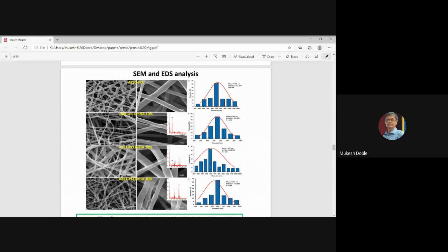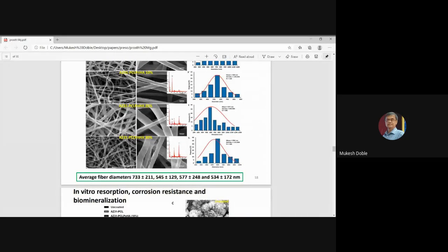These are some scanning electron pictures of the PCL coated surfaces actually. Different amounts of PCL, different amounts of hydroxyapatite we did, because our goal is to optimize the amount of HA so that we get uniform sized electrospun fibers. As you can see here, we got some beautiful fibers. Fiber diameter around 700 to 500 nanometers and so on. As I mentioned, we don't want to go into very low nanoscale. For cell proliferation, we need to reach a reasonably higher nanometer scale. So we were trying to go up to almost 700, that is 0.7 micron level.